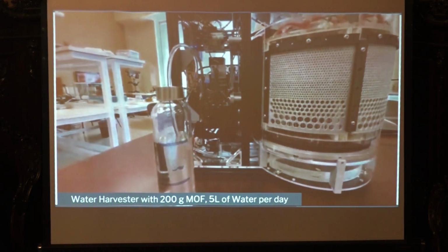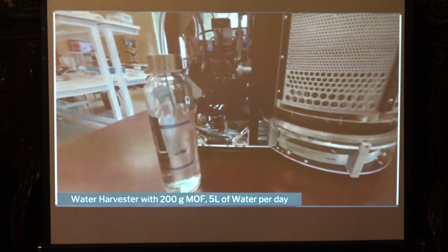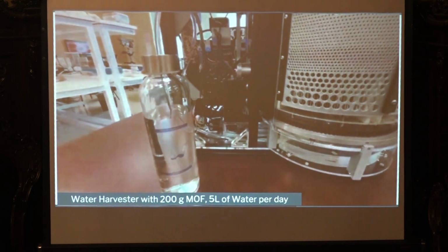You can harvest from this machine about 5 liters of water a day. This machine is no bigger than, let's say, a microwave oven in your kitchen. And it deploys only 200 grams of MOF. I want to repeat that: 200 grams of MOF give you 5 liters of water, and that 200 grams of MOF will stay in the machine for 6 years.